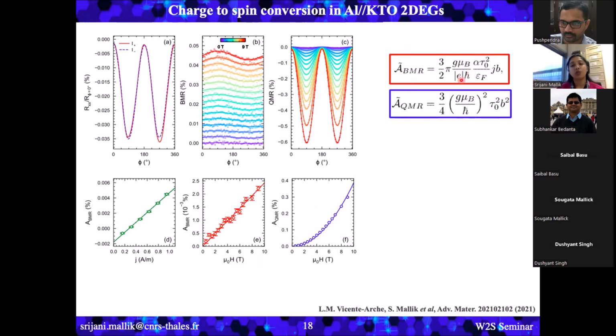So if we take a ratio between these two coefficients, then we can estimate the value of the Rashba coefficient from these measurements. So we estimated that the value of the Rashba coefficient is between 70 to 280 millielectron volt angstrom. And this is a really good agreement with the theoretical calculation. So we know that in our sample, we have really high Rashba spin orbit coupling present.